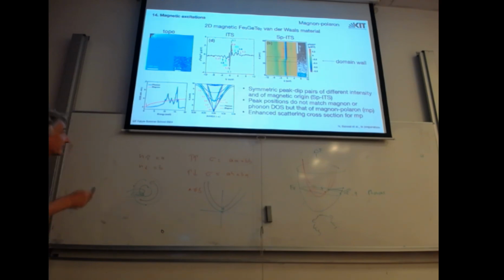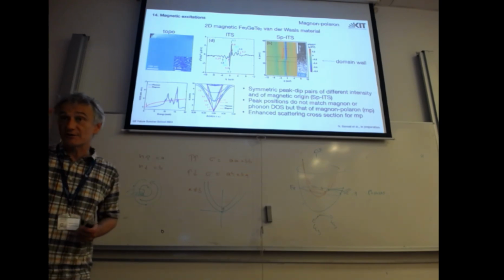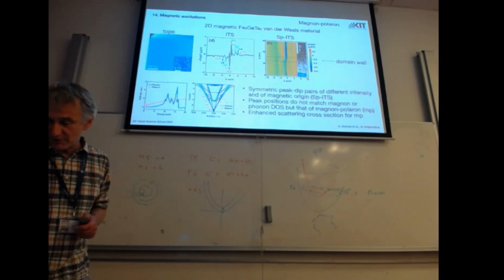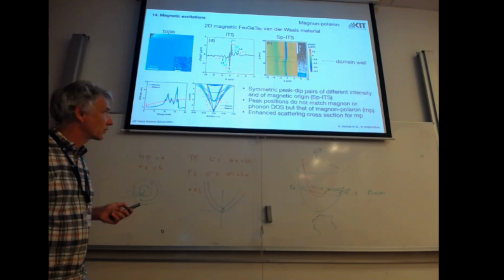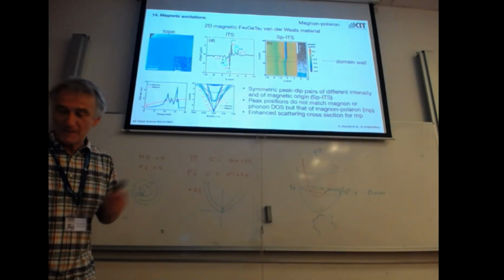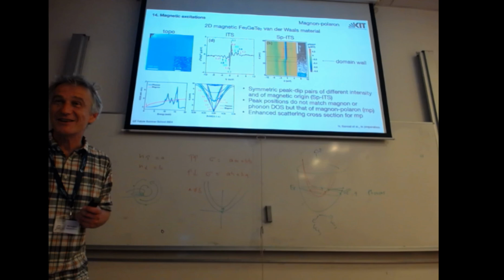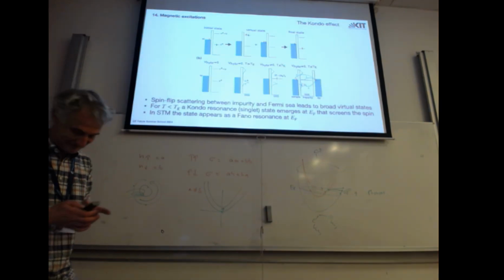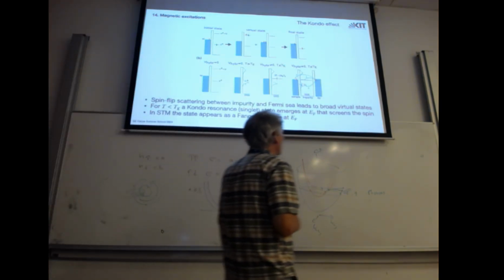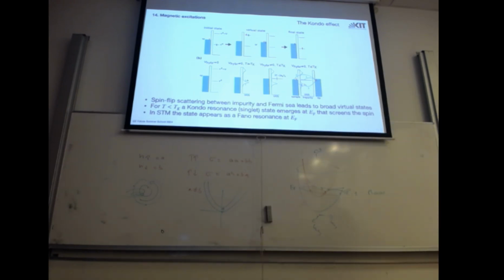Anyhow, the experimental observations, these peaks actually are exactly where the crossing points are. And we can apply a magnetic field and shift the magnon dispersion up and down, and you see these peaks moving left and right exactly following these crossings. So we are pretty sure that these are magnon-polaron bands. Okay. Let's see if the referee is also okay. There's another effect I want to discuss.